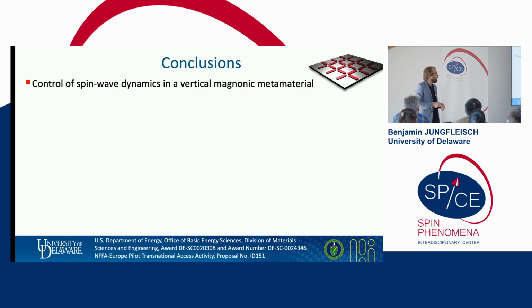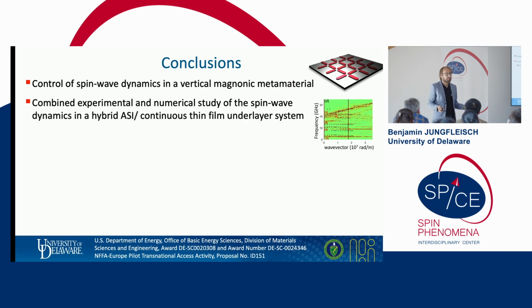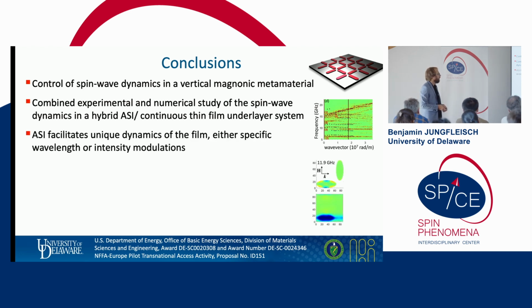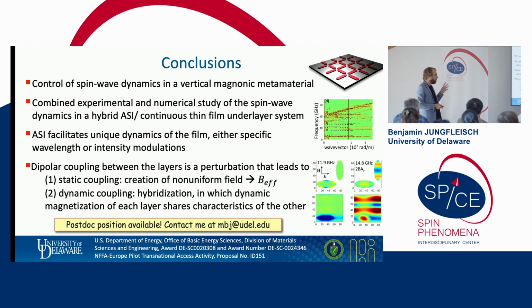I want to conclude. I've showed you that we can control spin wave dynamics in a vertical magnonic metamaterial. We combined experimental and numerical studies of this kind of hybrid system made of an artificial spin-ice and a film. The artificial spin-ice facilitates unique dynamics in the film, and we revealed two different interactions: static coupling, which creates a non-uniform effective field, and a dynamic coupling, which leads to a hybridization in which the magnetization of each layer shares the characteristics of the other.